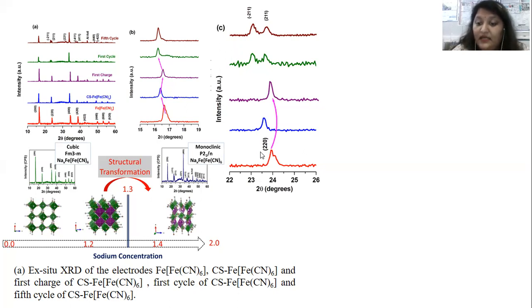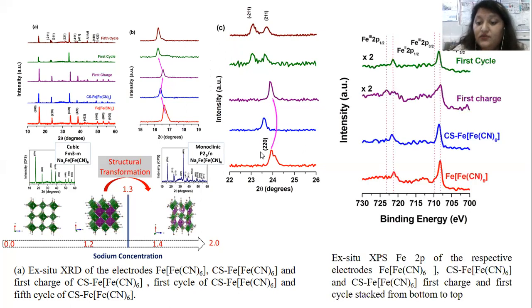The surface chemical analysis of the cycled electrodes through ex situ XPS study has been conducted on the composite electrodes, both as prepared and cycled. Apparently, the sodiated PBA and the first cycle show a similar Fe 2p spectrum with Fe2+ state, which is due to sodiation induced reduction, and is quite similar for both electrodes with only a trace amount of Fe3+.